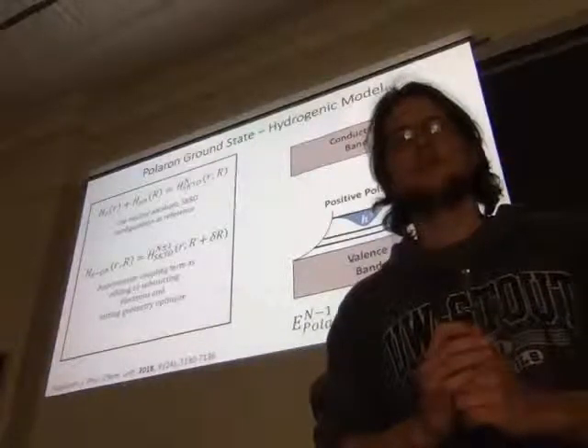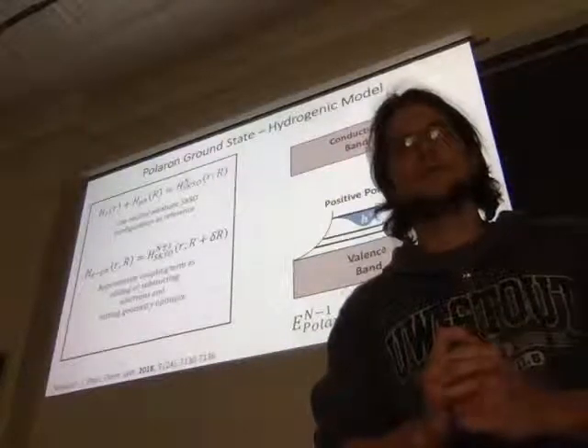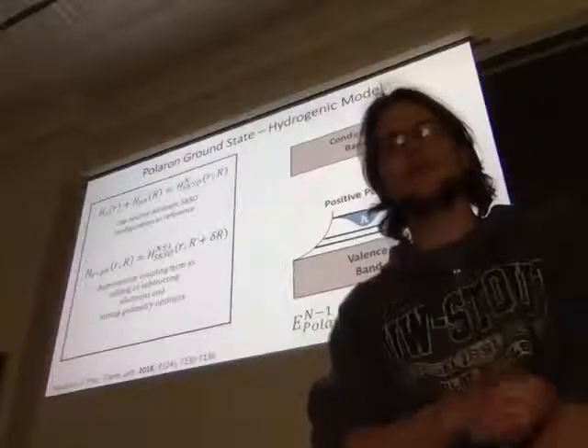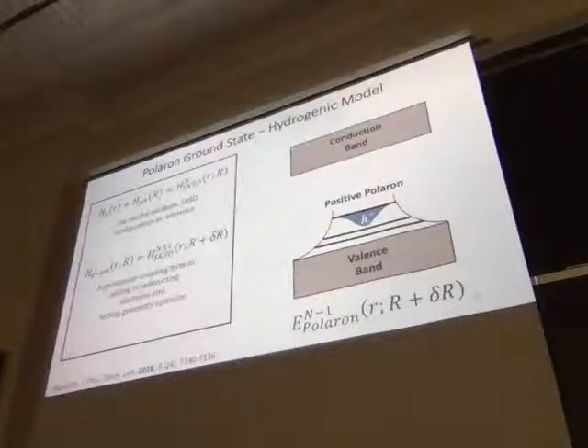You're correct, but it is hardly possible. If one would consider a polaron in the pure bulk material, then one needs to take into account non-zero momentum in the polaron, which adds an additional degree of freedom. So one needs to compute with periodic boundary conditions first, and recompute the different components. I'm thinking about some transition metal oxide. If you pull out one electron, you can see a small polaron almost right there. That's correct, but this material is a different type of polaron. Because in this case you may not have a small polaron, but a large polaron, and you may need a bigger system.